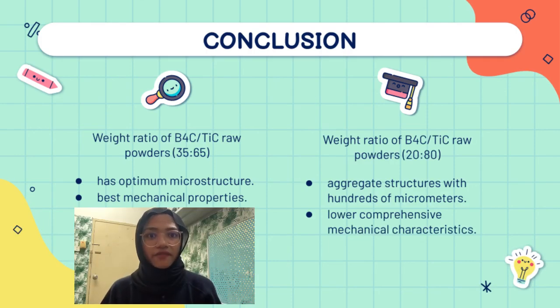Microstructure and phase components of the composites were examined. When the weight ratio of boron carbide to titanium carbide raw powders was 35:65, silicon carbide-titanium diboride ceramic composites demonstrated optimum microstructure and had the best mechanical properties. Lower comprehensive mechanical characteristics of the composites resulted from hundreds-of-micrometers titanium diboride and titanium silicocarbide aggregation structures, which occurred in the manufactured composites when the weight ratio of boron carbide to titanium carbide raw powder was 20:80.